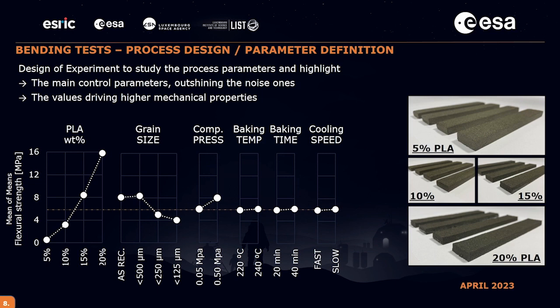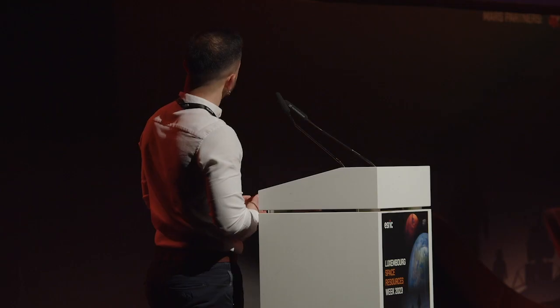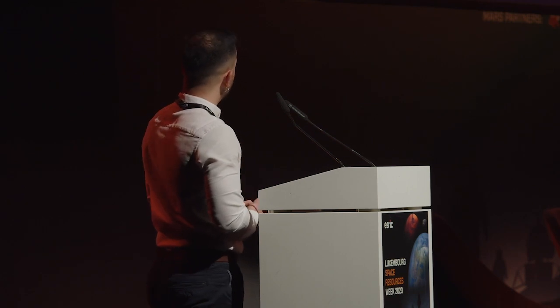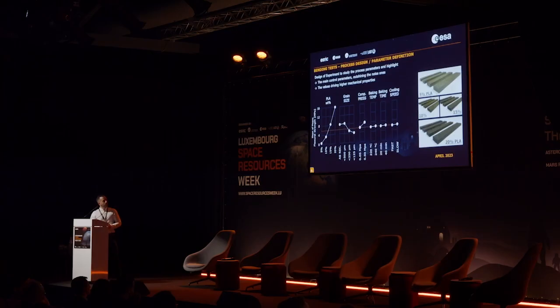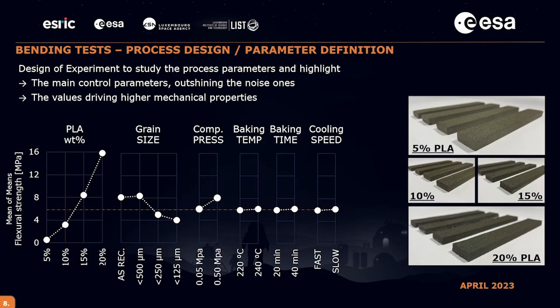At the same time, it confirmed the effect of the percentage of binder, and it tells us that we don't need to sieve the regolith to have only the finer part of the granulometric distribution, because the as-received regolith was already good enough. It also confirms the effect of the pressure. You will see that the values of the compression pressure here are lower than the ones you saw in the previous slide, and the reason is only due to the dimension of the specimen. So with that hand press, we could not compress those specimens, which are bigger, with a pressure higher than 0.5 megapascal.